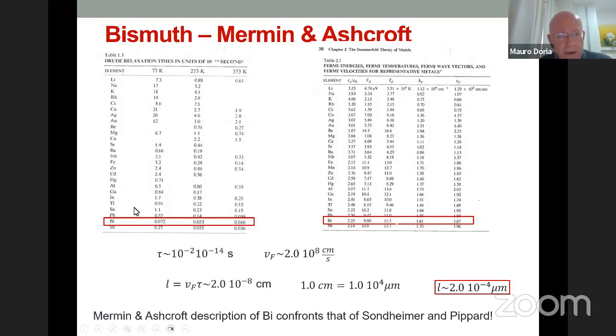In fact, if you go and look at Mermin and Ashcroft, they use the Drude model to compute. They take the resistivity of bismuth, obtain the Drude relaxation time, and so forth, and they obtain the mean free path out of this, and they are completely wrong. They give values of 10 to the minus 4 micrometers. So this Drude model does not work for bismuth. The information that they provide for bismuth confronts what Sondheimer and others say. This is interesting. It's an error in bismuth in Mermin. This is my opinion; I never found this comment in any other place. It came from my mind. So if you find that there is something wrong, please let me know. But if you read off what they give here for bismuth parameters, you find out that it leads to a wrong mean free path.